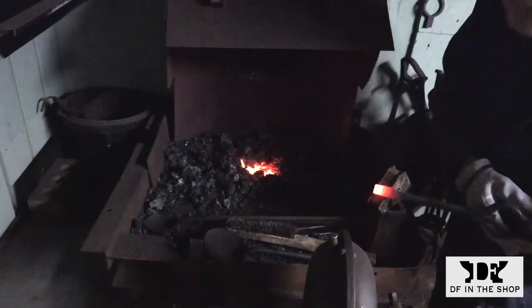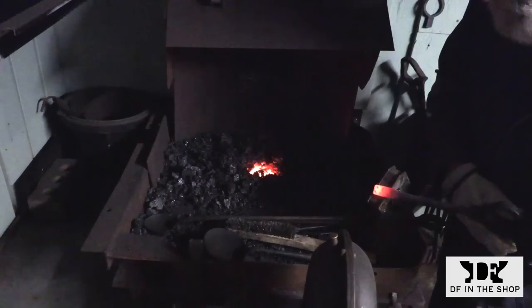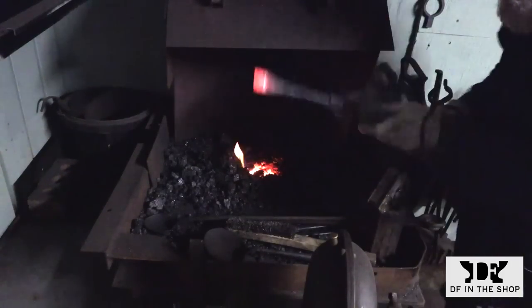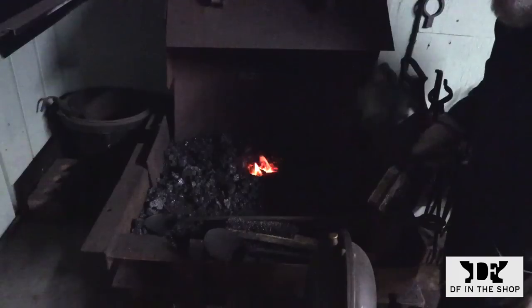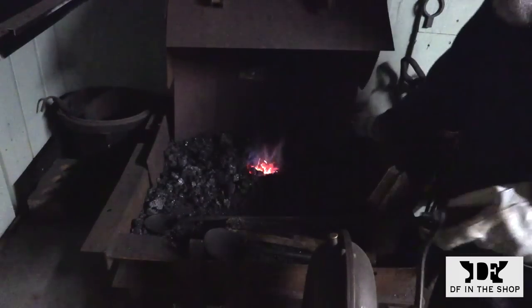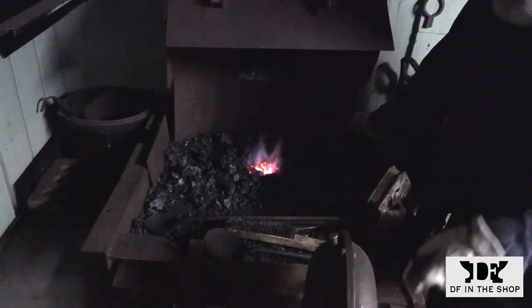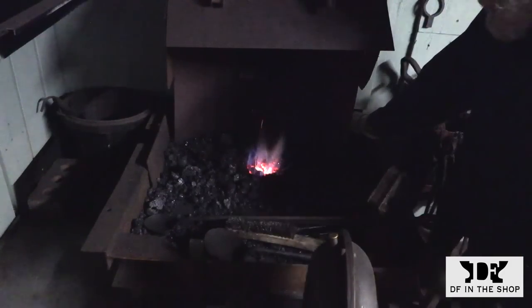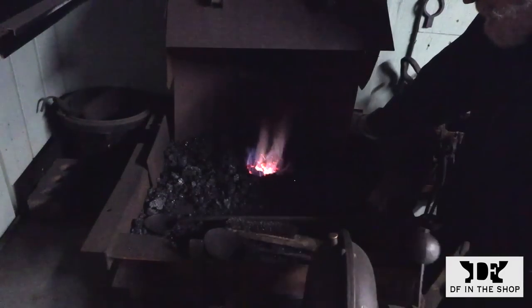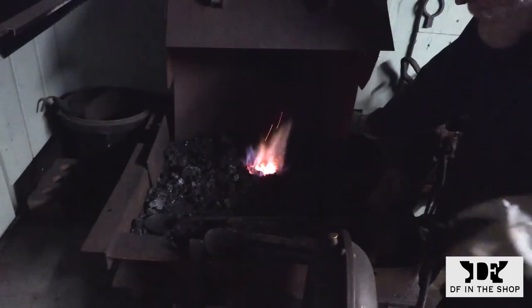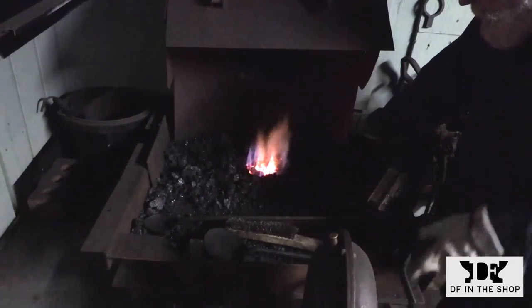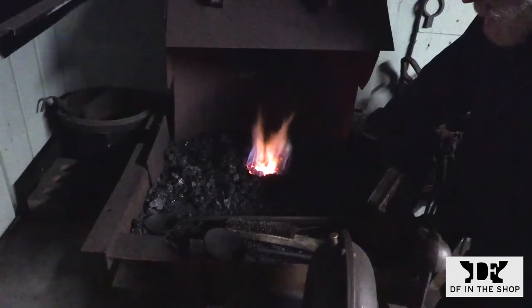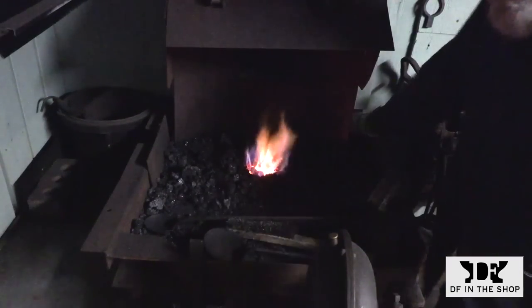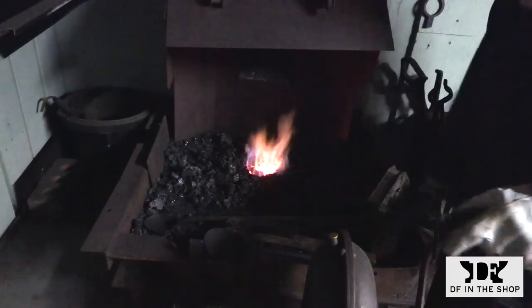So here again, it's hotter still, but we're checking it with a magnet, so most people would think, okay, we're still in the critical temperature range, but as you know, we're well above it now. And the grain structure is still getting larger. And the larger the grain structure, the weaker the steel is. So even though the outside of the steel may appear hard and this file will skate off it, and all the usual things, the internal structure is very weak because it's very granular, and the steel is literally starting to blow apart.